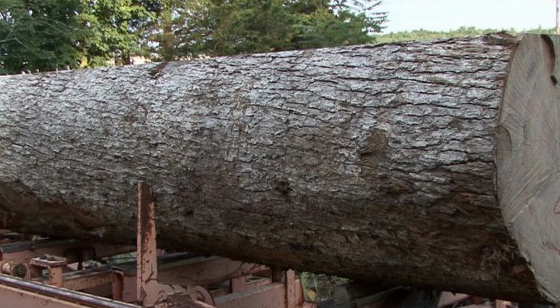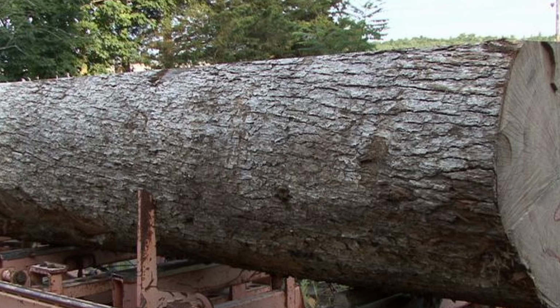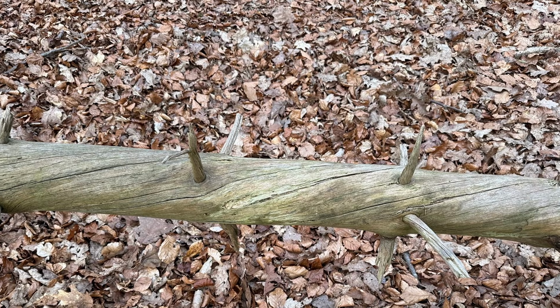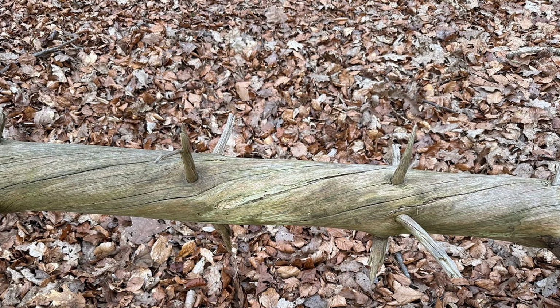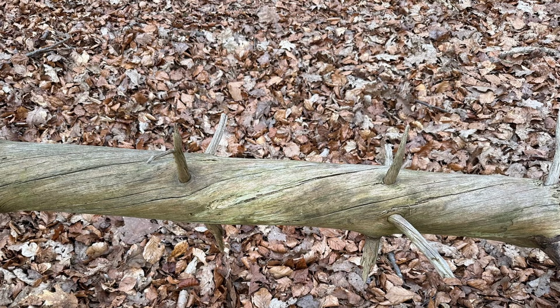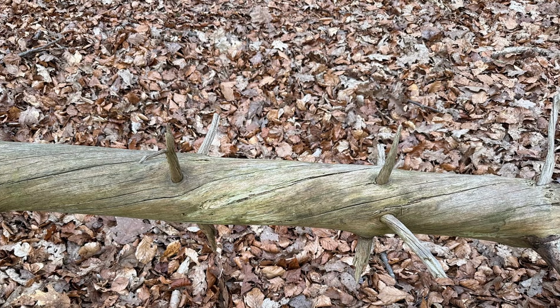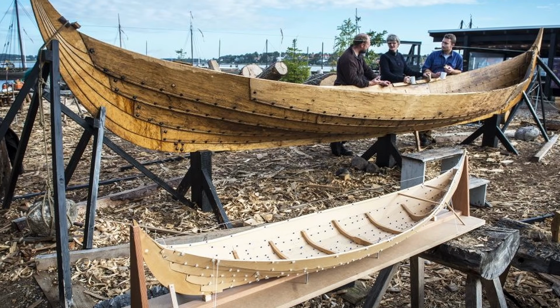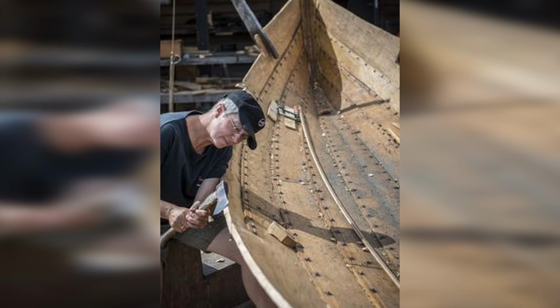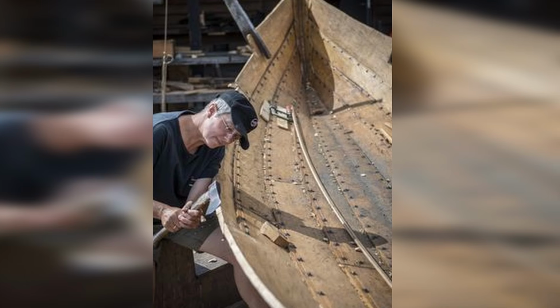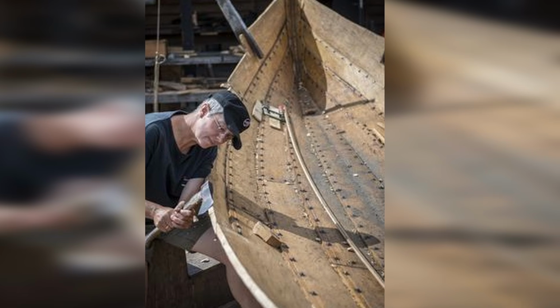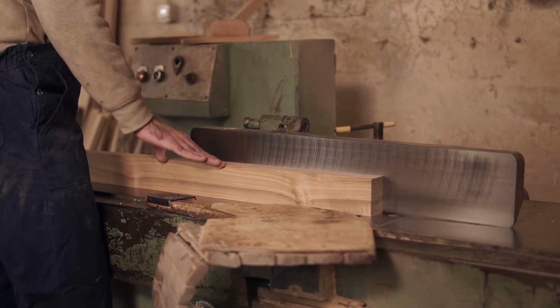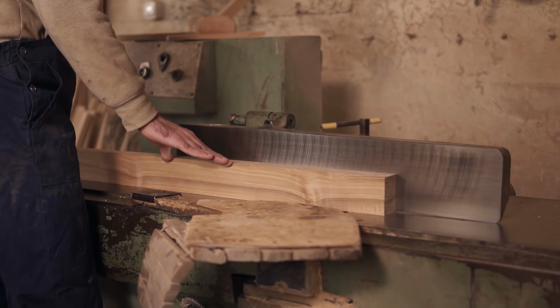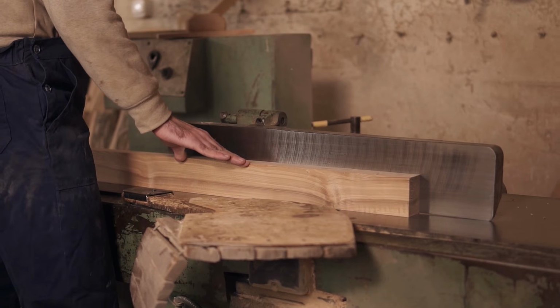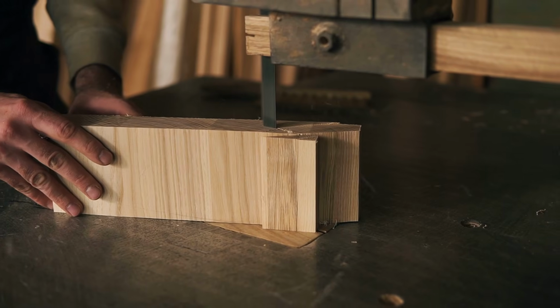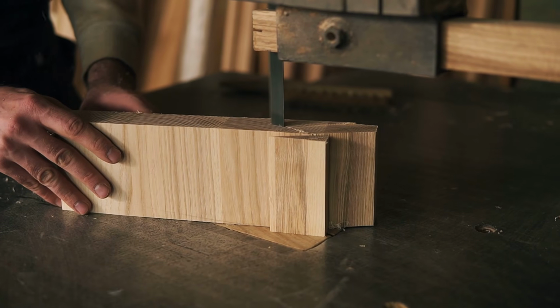But splitting has a quality control requirement. If a tree has spiral grain, where the fibers twist around the trunk, the split will follow that twist. You'll get a warped board that's useless for a ship's hull. So Viking builders had to carefully select only the straightest trees. This acted as a natural filter, ensuring only the highest quality timber made it into the ship. Modern sawmills can force straight boards out of twisted logs, but the resulting lumber has short grain, weak spots where fibers were cut that cause it to fail under stress.